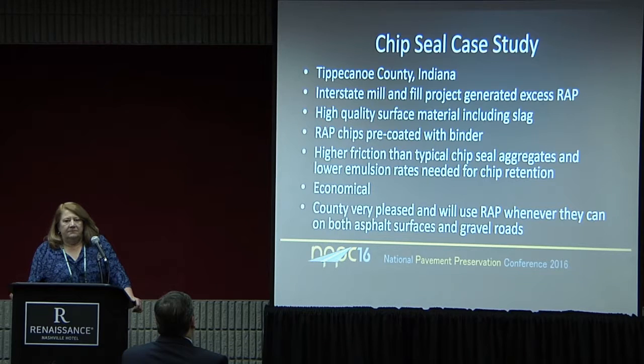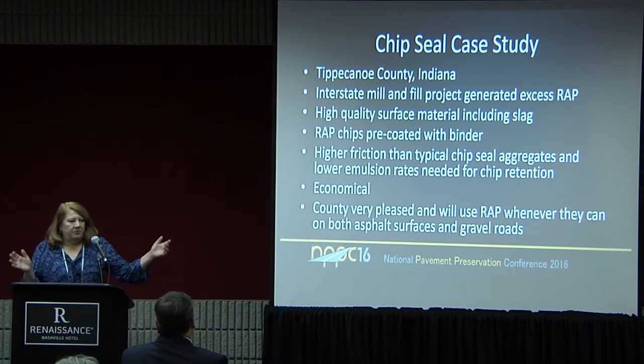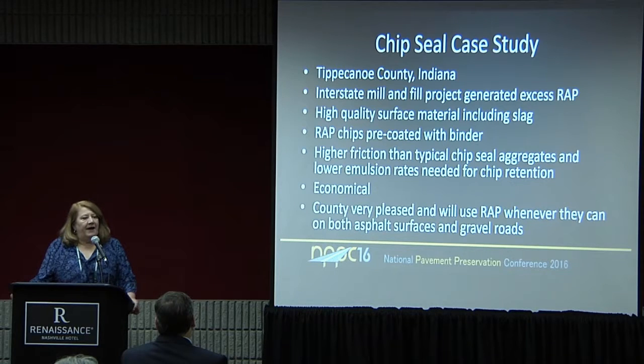On Interstate I-65, they had a big mill and fill project that generated excess RAP. And in Indiana, the contractor owns the RAP. So they had this pile of RAP, and they couldn't reuse it all back in the mill and fill operation. So they provided it to the county, and the county did some chip seals with the product. So they got slag aggregate in their chip seal, nice dark colored steel slag.